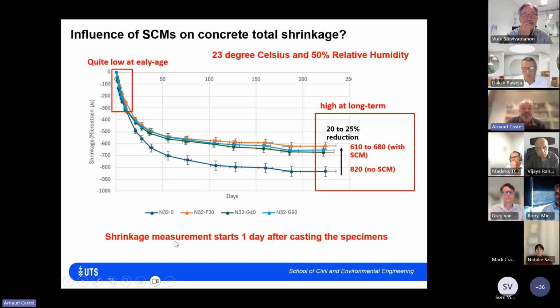Everything I will be showing from now is shrinkage where the measurements start at day 1, not day 7, and the specimens are stored in a standard condition. So what we can see is that at long term, yes, there's a difference, 20–25% for concrete with SCM. Not much difference at early age. Well, if I could zoom, you would see a difference, but it's not as much as for long term. So it's already good to know. We're not seeing a lot of influence of the SCM for early age, for that example at least.